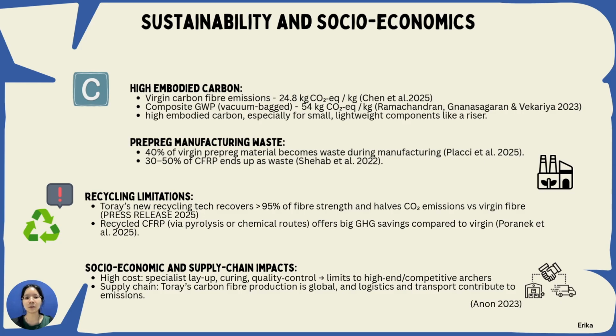Producing virgin carbon fiber is carbon intensive. According to Chen et al., industrial scale production emits around 24.8 kg of CO2 equivalent per kilogram of fiber. When we convert that fiber into a composite like in our riser, the global warming potential can rise to about 54 kg CO2 equivalent per kg, as shown by Ramachandran and Ganasagaran. Because our riser is lightweight but long-lived, these upfront emissions are a major part of its environmental footprint.